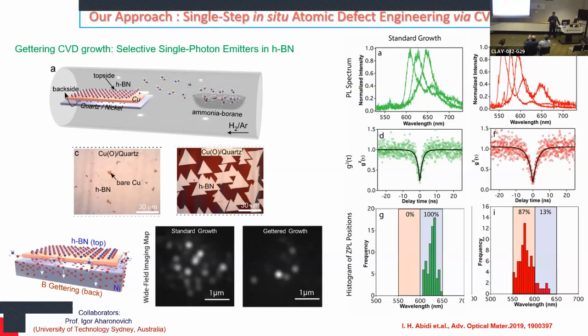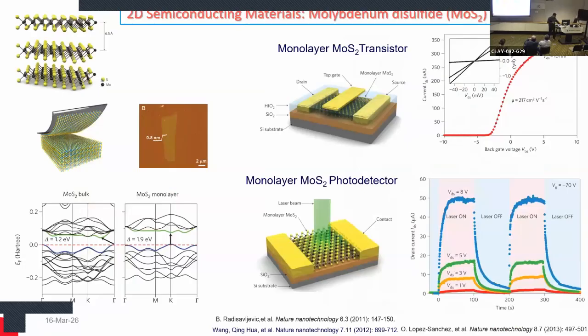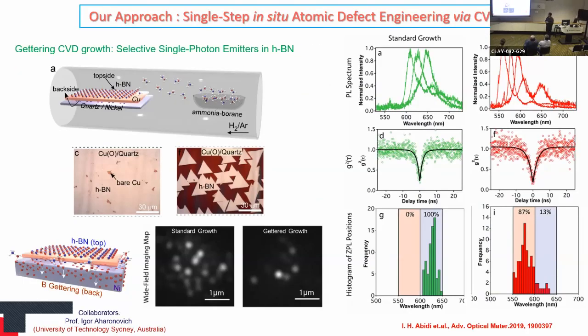What's the purpose of the copper substrate here? What role does it play? For the copper substrate? Yeah, why do you need the copper substrate? So boron nitride also grows similarly to graphene, so it requires copper as a catalyst. Yeah, also a catalyst. Yes. Thank you. So again, we use copper as a catalyst, and then we grow boron nitride, and then you can transfer it to any substrate you want.